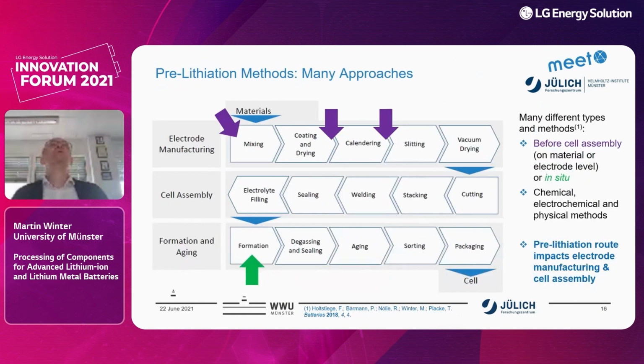And with this method now we can go into pre-lithiation as a process. Pre-lithiation is a process that should be incorporated in the segment-wise steps of cell assembly and cell making. So we have electrode manufacturing, cell assembly, and formation and aging. Depending on the pre-lithiation method, you can apply pre-lithiation during the electrode manufacturing, but also during formation and aging, especially during the formation process. And the pre-lithiation route, because we have different pre-lithiation processes, there are, let's say, half a dozen at least, impacts the electrode manufacturing and cell assembly.